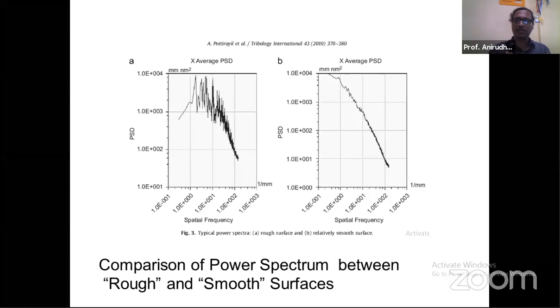You see, there is a large demarcation, a large difference about the information this power spectrum from this rough surface is trying to give as compared to the information related to the power spectrum from a smoother surface. So therefore we thought, why don't we use information related to these power spectra to deduce something out from them, to formulate perhaps one parameter or more than one parameter which can explain those friction values. Now, how do we say that they would explain? Because they should give a higher correlation between the features of what we are trying to include in our parameter and those friction values.